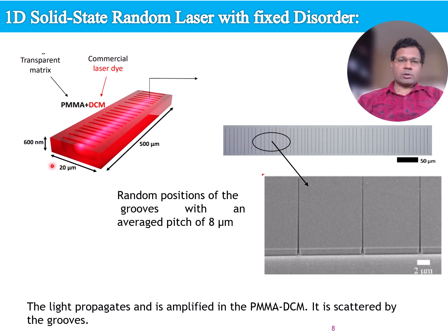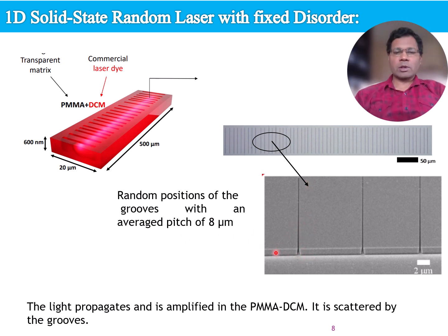To fabricate 1D disorder structure, we use E-beam lithography to carve 62 randomly distributed parallel grooves into a PMMA DCM layer. Each groove was 200 nanometer wide and 50 micrometer long, spanning a total length of 500 micron. That means all 62 grooves are distributed over a length of 500 micron. The average spacing between the air grooves was approximately 8 micron, which creates a controlled disorder pattern suitable for studying random lasing behavior. This is the optical microscope image of the whole disorder system, and this is the zoomed-in high resolution SEM image of a few air grooves.